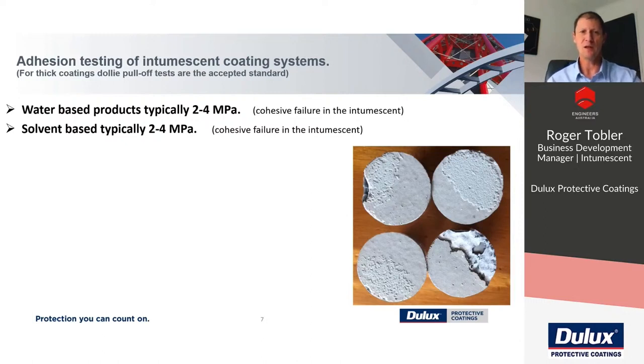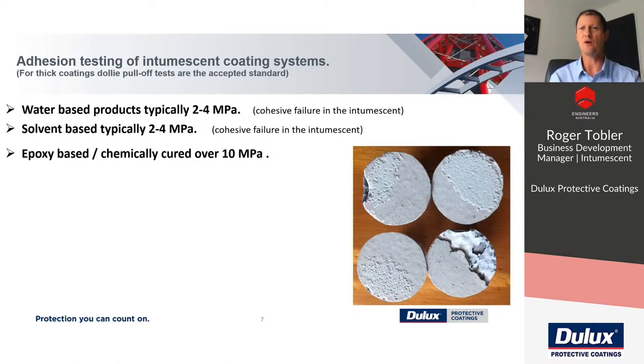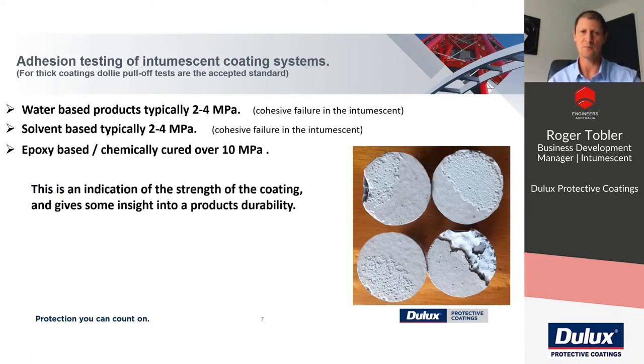Enter the exception, and these are the epoxies. And what you find with the epoxies is that they're chemically cured, they're really strong coatings, and you find far larger adhesion values. And often the failure here is no longer in the intumescent. It's the primer, the top coat, that starts to fail because the intumescent is much, much more durable than a solvent-based or a water-based product.